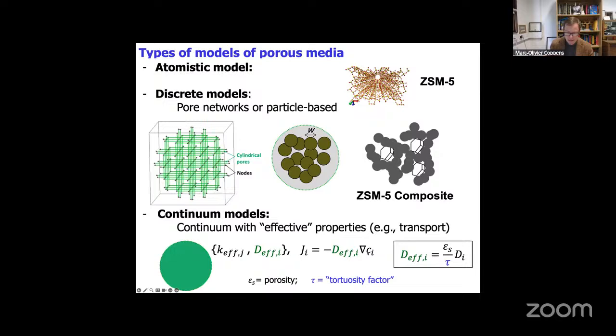And so the work of Zhang and Seaton already in the 1990s showed that if they compare a model with explicit pore networks and compare it with a continuum, you get very good agreement. You can fit a tortuosity to it and it works really well. It is when percolation effects start to play a role, when you have multiphase situations, when you start to have surface barriers, then it is really important.